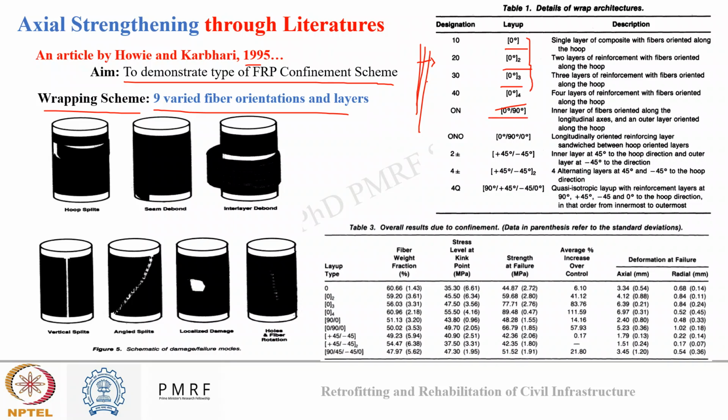In the fifth case, my fibers were oriented both along the length and perpendicular to the length. Then there was one case with three configurations, longitudinally oriented reinforcing layers sandwiched between hoop oriented layers. There was plus minus 45 degree orientation, two layers of plus minus 45 degree orientation, and 90-45-45-0 degree orientation. For these nine configurations, they calculated the maximum strength the column was able to take,